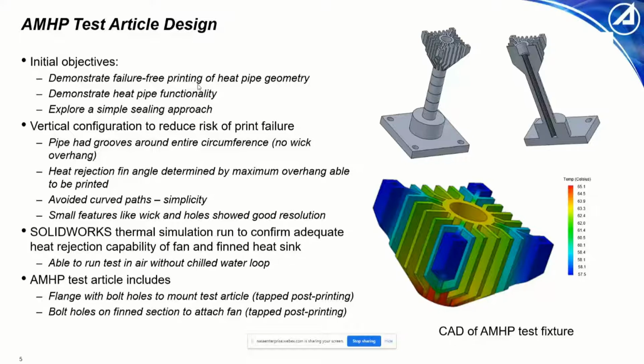So our goal was to create a simple approach that would allow for reproducibility of results and long time usage of our hermetic seal. We elected to use a vertical configuration in order to reduce the risk of any print failure. In doing so, we're allowed to print grooves around the entire circumference, so there was no wick overhang.